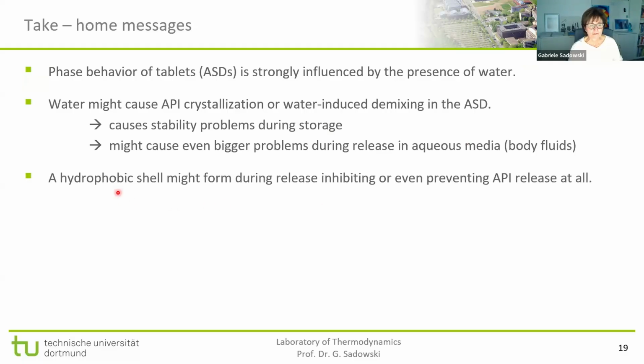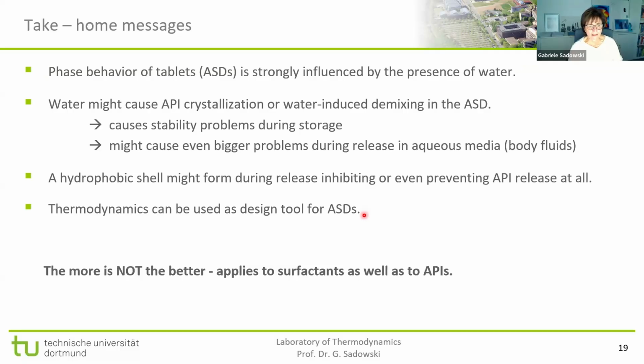So that means that, depending on the systems and the phase behavior, there might form a hydrophobic shell, and this can decrease or even inhibit the API release, and this is obviously not what we want to have. And if we understand this based on a phase diagram, we can, of course, do the calculations and also predictions and suggest the components that might help to avoid this problem.